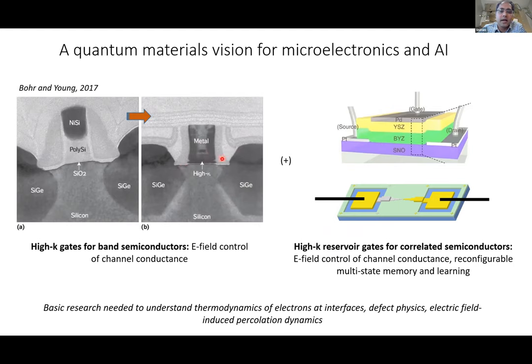Conceptually, practically it's a different matter, but conceptually, the high-k could serve as an ion reservoir and enable all these different wonderful properties that I just showed. That is possible by not just sustaining an electric field, but to use the electric field to move charges or electrons in massive numbers that are required for these types of correlated semiconductors, orders of magnitude more than what is sufficient for silicon or germanium. So I think this is a really interesting research direction. We need to understand lots of things about this. We are just starting to scratch the surface.